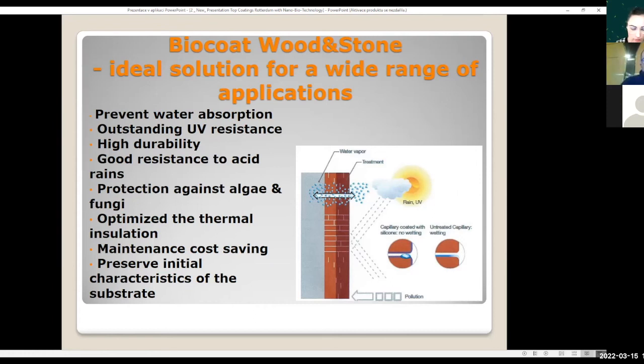There are some more effects, not only from this slide, but also the influence from the atmosphere, when exhausts from engines are mixed with dust and others, and it has a corrosive influence on the building construction. We also need to reduce the temperatures as much as possible. Another possibility is to coat the asphalt roads, for example. We reduce the exterior temperature because the asphalt will not be overheated. I have experience from my country. We do not have such high temperatures, but during June and July we can have 40 degrees.